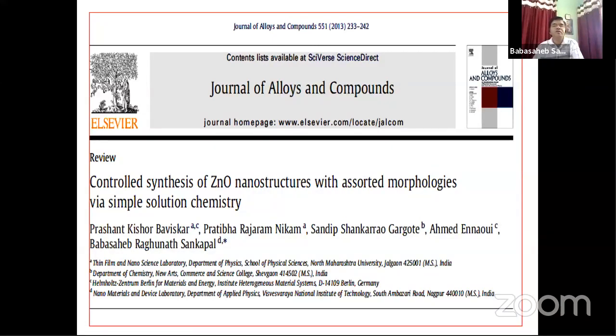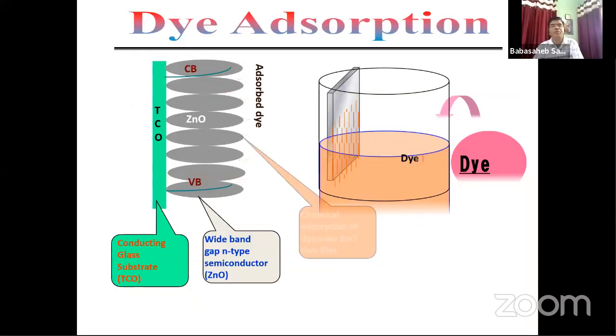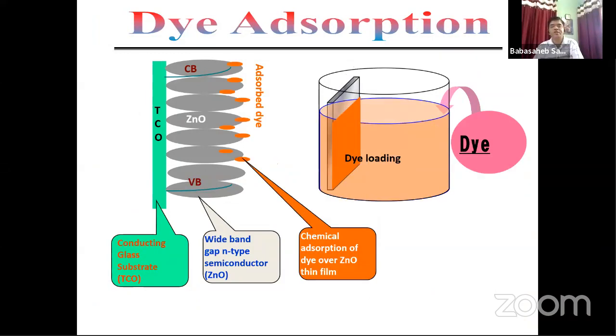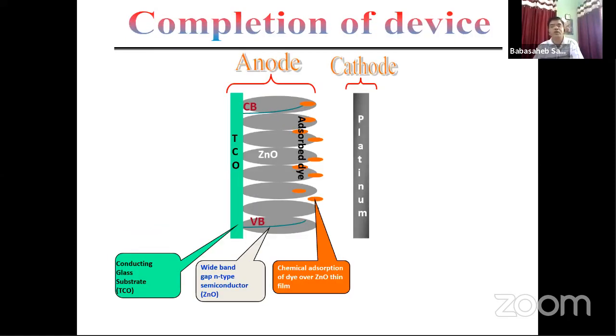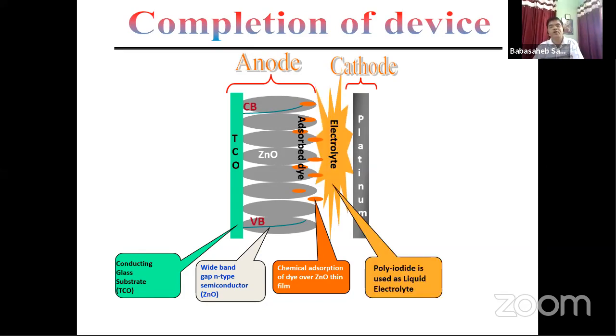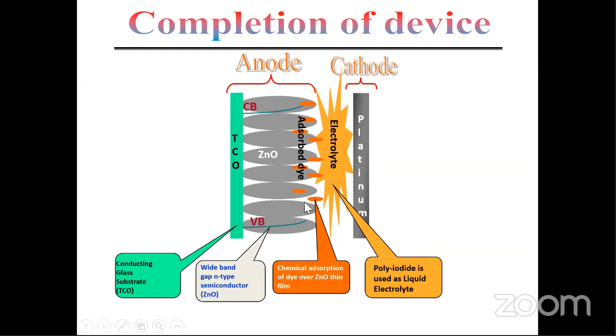The next step is the dye adsorption. One monomer of the dye has to be adsorbed on the high surface area of this zinc oxide. We have used an ethanolic solution of the dye molecule. Then we have used a liquid electrolyte, that is the polyiodide liquid electrolyte, which is placed between the dye-coated zinc oxide and platinum as a back contact. Capillary action is used to place this liquid electrolyte between the two electrodes, the cathode and the anode.